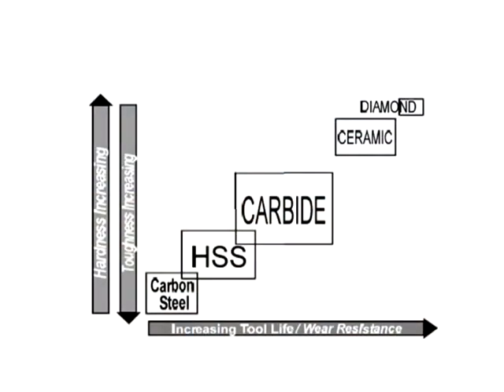There again, your carbon steels, your high speed steels. Next comes your carbides. Tungsten carbide's probably the most common one you'll find. Then you can get into some ceramic and diamond. Your ceramics and diamond tend to be for metal. But with the ceramic, you can turn a Rockwell C60 heat treated part.